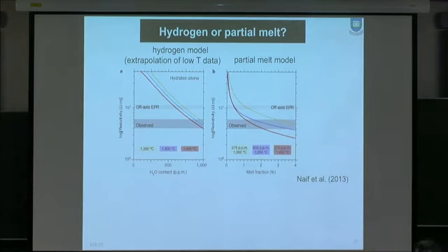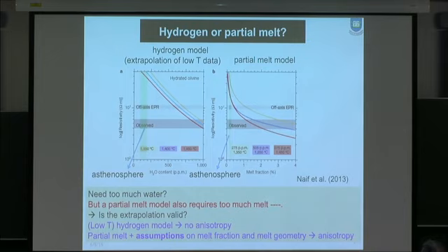There was an interesting paper to evaluate the hydrogen model versus the partial melt model published 3 years ago, in which the authors calculated the expected water content from the hydrogen model and the expected melt fraction for the partial melt model. They concluded that with the hydrogen model, to explain the observed conductivity, one would need this much water, which is much higher than the water content we expect in the asthenosphere. So therefore, they rejected the hydrogen model. However, for the partial melt model, the amount of melt that they need is in this range, 2, 3, 4%. That is much higher than the amount of melt which we expect in the asthenosphere. So therefore, I conclude that both the hydrogen model and the partial melt model have very serious difficulties in explaining those observations.